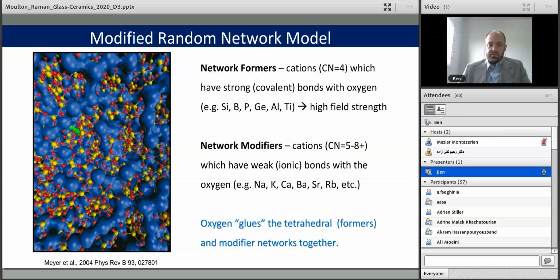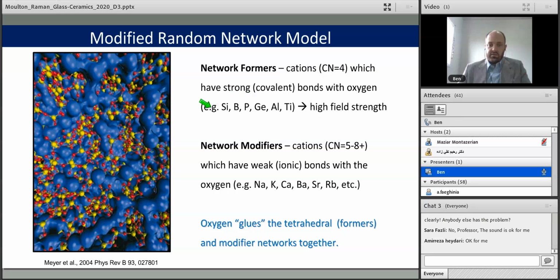So this picture, to understand the structure, we sort of divide it into two elements. Those elements which form the network, and these are the silicon tetrahedra, for instance. They almost always have coordination 4, although this can be changed. For instance, boron will have 3-fold coordination. And these elements usually have strong covalent bonds with oxygen, and they're the part of the network that remains constant between the crystal and the liquid.